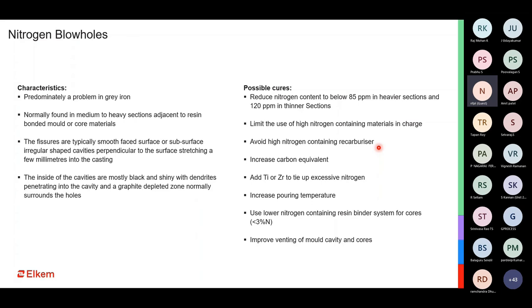Possible cures: we have to control the incoming nitrogen into the system. Where does the nitrogen come from? It can come from the materials in the charge especially, and also the recarburizers that we use in the system. How do we solve it? We can have a much higher carbon equivalent. What does it do? It ensures that you have a lot of graphite precipitation, and thus restricts the fissure defect from flowing into the cavity.